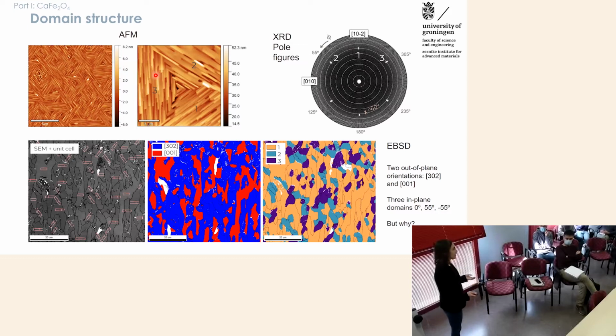And what was immediately clear is that the structure of this material was not super simple. It was actually formed by at least 3 different in-plane orientations. So the film is composed of these elongated needle-like crystals, and all of them come in 3 different in-plane orientations. Here you see 1, 2, and 3. And by different measurements, for example, this is an XRD pole figure, we could indeed see that these 3 peaks correspond to the 3 in-plane orientations of the crystal.